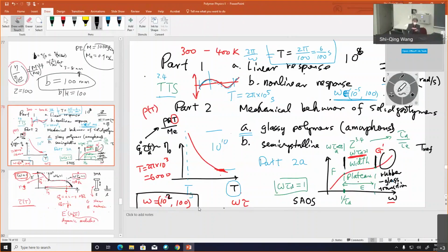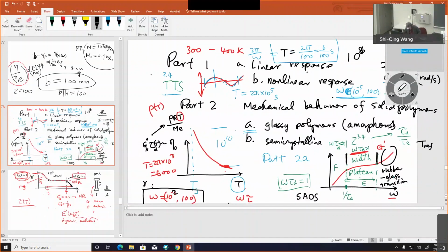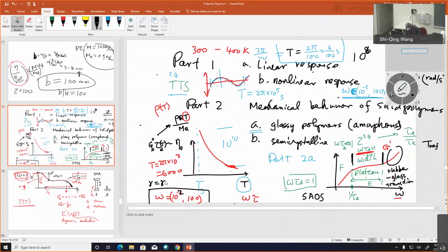So basically, you load the machine, you choose an amplitude, which is typically small, so you don't agitate the sample very much. You don't go to the wall slip limit. You just heard last time. Wall slip doesn't occur at a small amplitude, okay? Because you have to disentangle. That requires a lot of strength.